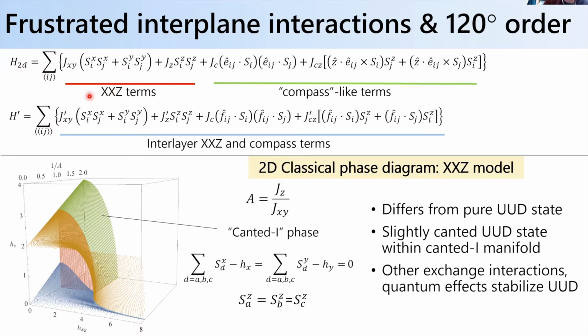Okay. And then basically further looking at the XXZ terms under a magnetic field, they can develop a magnetic phase diagram of the system. And the predicted state under applied field is what they call this canted one phase, which is slightly different than the up-up-down state, meaning it's akin to an up-up-down state where all the spins have been canted slightly out of the direction orthogonal to the direction that the moments are pointing within the ideal up-up-down state. So, resolving the discrepancy between these two, it could be that the neutron scattering is just not